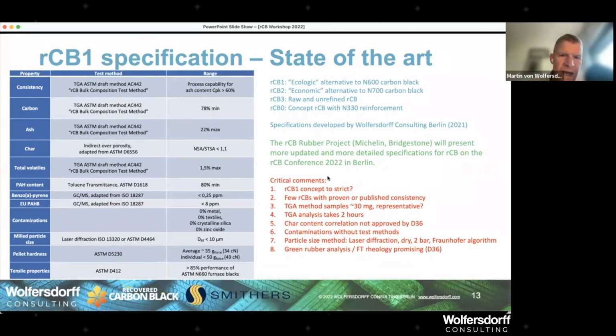So the main reason I look at my own specification with a critical eye is: is it too strict, the rCB1 concept? And there are also a couple of points which I could criticize. There are very few recovered carbon blacks as of now with proven or published consistency. Boulder Industries were the first in the world to publish about a whole year of measurement of ash content and published a white paper about recovered carbon black consistency. That is fabulous. But any tire maker from any recovered carbon black producer needs consistency. And if there's only one thing which is fulfilled in the specification, it should be consistency. If a recovered carbon black is consistently bad, it can be used in the tire industry. It might not have the highest value, and there are, of course, some showstoppers, but consistency really is super important.